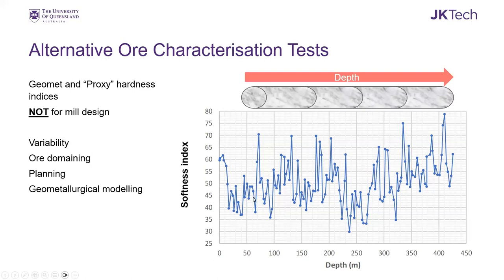So we can get all this noise with tests that are not very exhaustive when it comes to the energy applied or the particle size selection for the test. So we get very noisy data. For example, on this top of the pit, we can get an average around 45 or 50. But if we get the last pit at the very deep of that mine, the average using this measurement can be between 55 and 60. But it really comes to